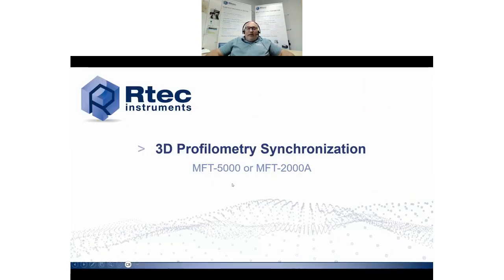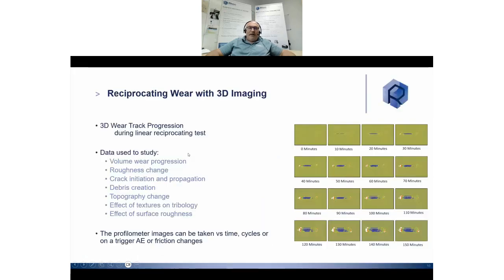The idea to have something new with tribology was the fact we combined 3D profilometry with our tool. And for example, here we have a reciprocating wear. We are testing some steel materials, and we decide to take a picture of the stroke every 10 minutes. And you see 0 minute, 10, 20, 30, and we took an image automatically synchronized.